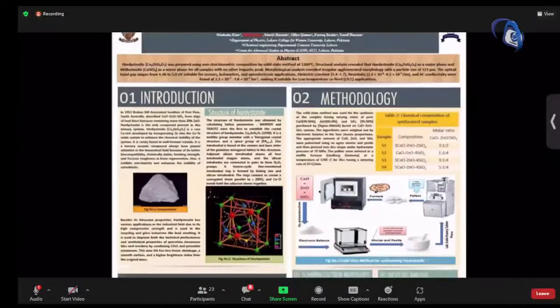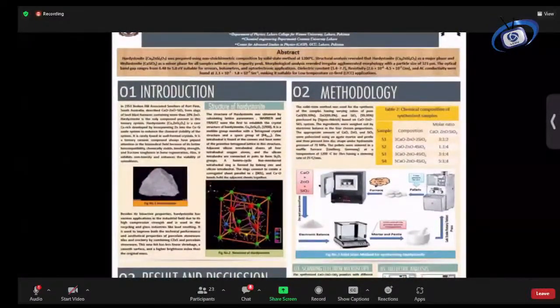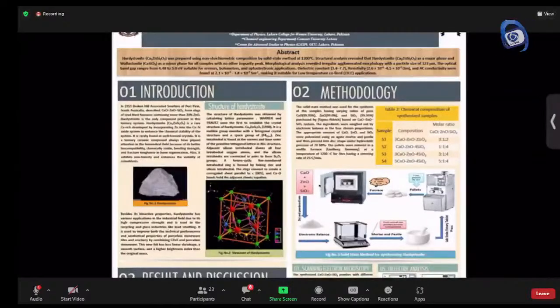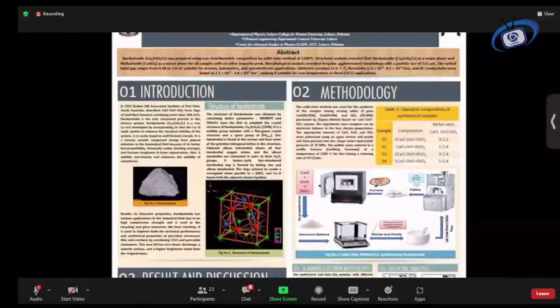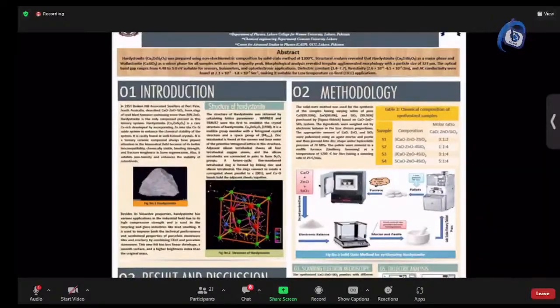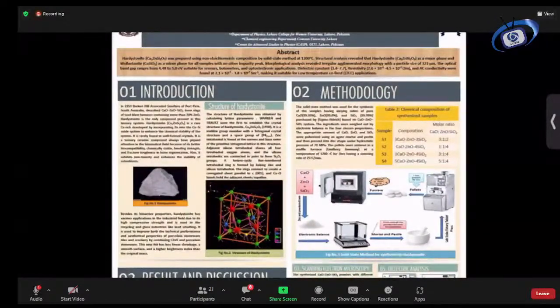So if we talk about the introduction, Hardystonite is a tetragonal structured element. In 1953, Broken Hill Associated Smelters at Port Pirie, South Australia, described calcium zinc silicon oxides from slag furnaces. So Hardystonite is a rare calcium-rich compound developed by incorporating zinc into the calcium silicon oxide system to enhance its chemical stability for applications. It is a ternary compound that has attracted attention in the biomedical field because of its better biocompatibility, chemical stability, bending strength, and structural toughness in bone regeneration. So the aim of my research: as it has attracted attention in the medical field before, but there is no evidence to calculate its optical and dielectric properties, which I have done in my research.